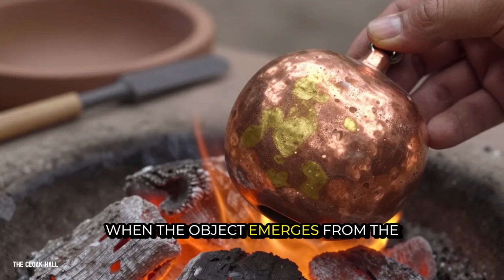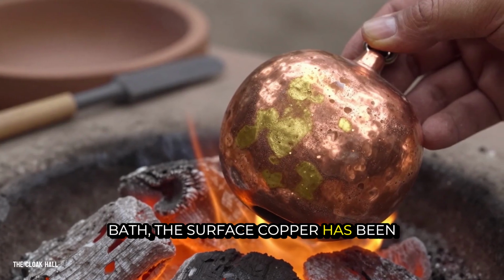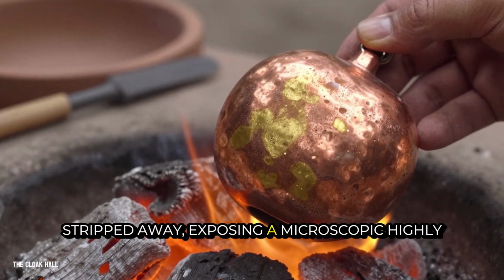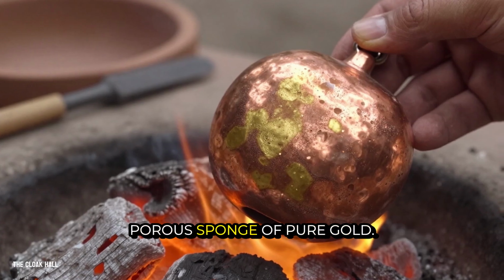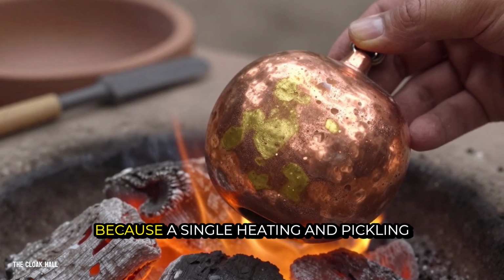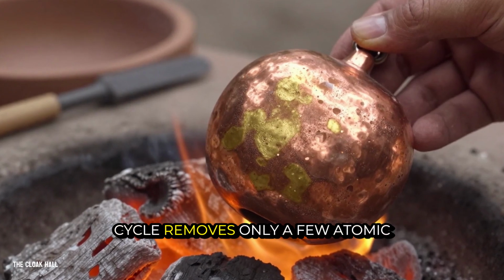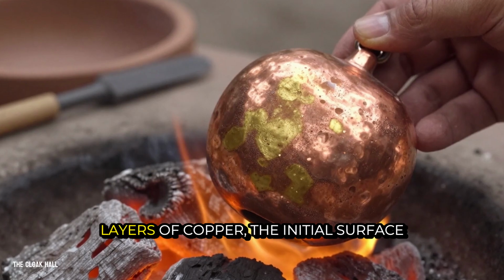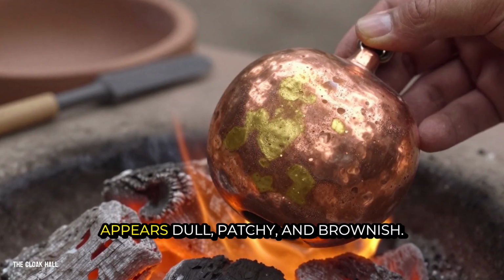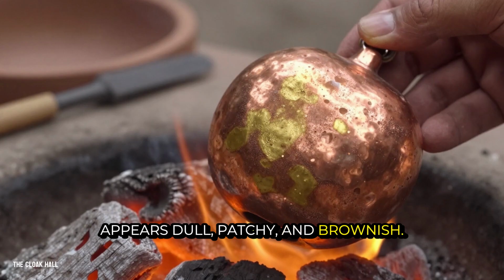When the object emerges from the bath, the surface copper has been stripped away, exposing a microscopic, highly porous sponge of pure gold. Because a single heating and pickling cycle removes only a few atomic layers of copper, the initial surface appears dull, patchy, and brownish.